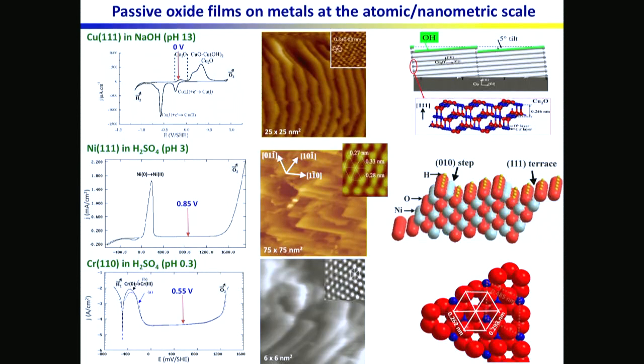And the last example I'd like to show for pure metals is the example of chromium. So once again, this is in acidic solution. This is the polarization curve with a dissolution and then passivation. And we looked at this potential, and this is the image that was recorded. So again, you can see terraces, steps, highly crystalline oxide according to the high resolution STM image. And again here, the oxide, you see the hexagonal structure.